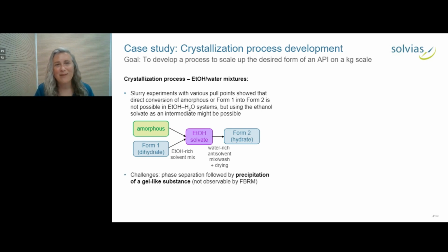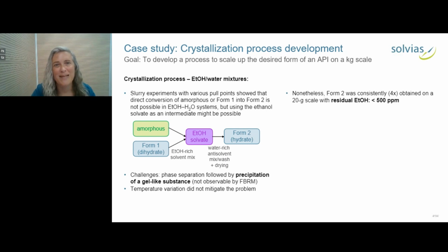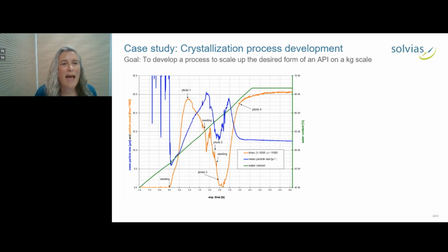What was challenging was that we found there was some phase separation and then precipitation of a gel-like substance. We tried this at different temperatures, but it didn't help. Nonetheless, these first trials showed that we could reproduce it on a 20-gram scale with acceptable levels of residual ethanol. But because the process was slow, because we had these gels and other intermediate phases, we needed to optimize it more. Here you can see an example of an FBRM readout.